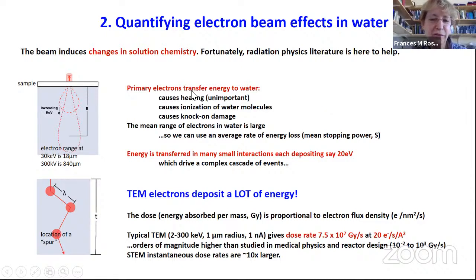The primary electrons transfer energy to water, and they transfer it in lots of little interactions, each depositing, say, 20 eV worth of energy. Remembering that the electrons started out with 200 kV energy, they do not stop typically in the sample. They pass through, they lose a tiny bit of energy, they lose energy along their path. And so this makes it quite easy to calculate how much energy is being deposited into the sample. And it's a lot of energy. So here's the dose rate for a typical TEM experiment.